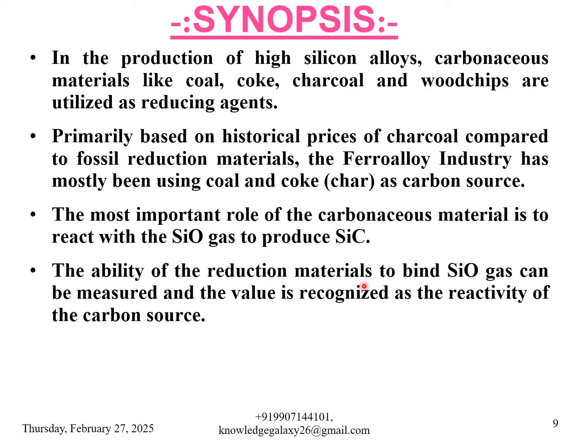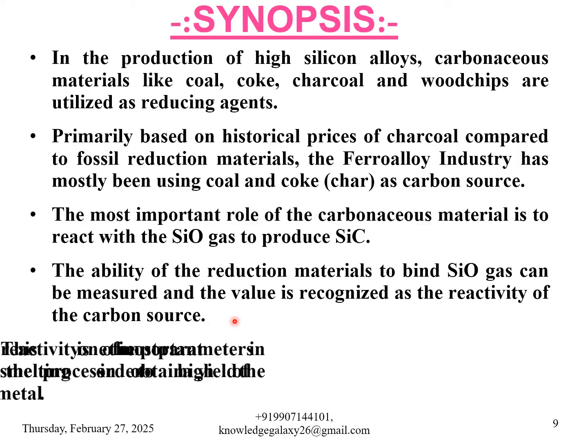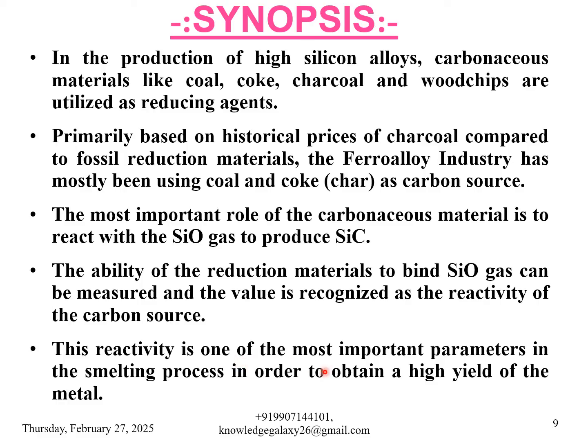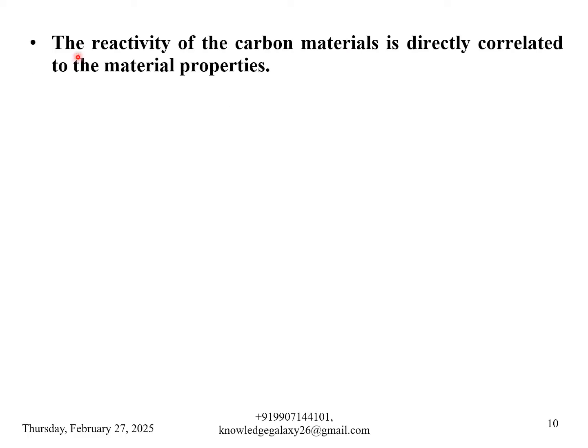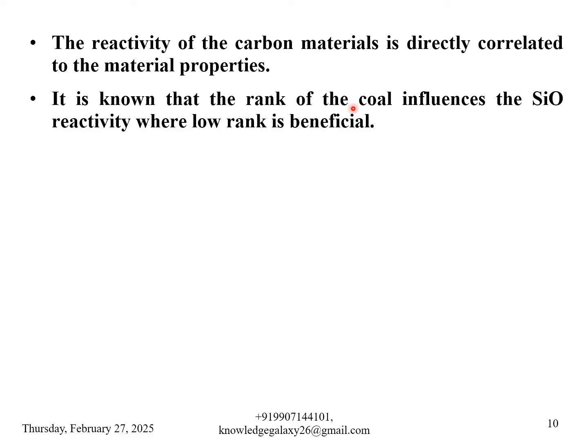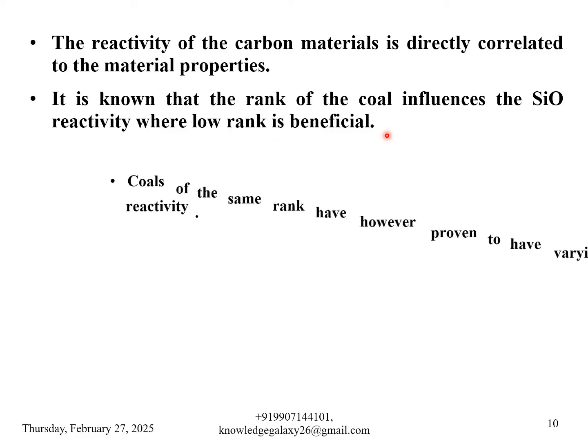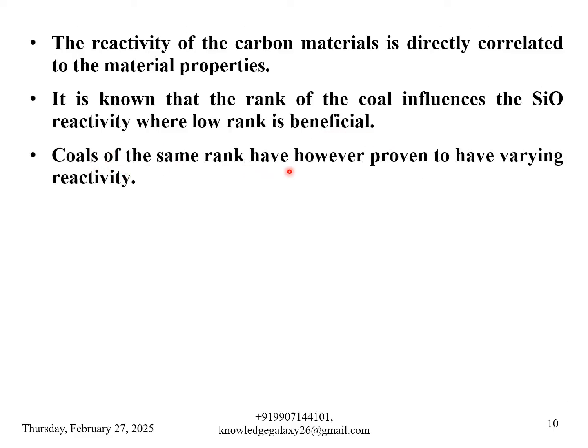The ability of the reduction materials to bind SiO gas can be measured, and the value is recognized as the reactivity of the carbon source. This reactivity is one of the most important parameters in the smelting process in order to obtain a high yield of the metal. The reactivity of the carbon materials is directly correlated to the material properties. It is known that the rank of the coal influences the SiO reactivity, where low rank is beneficial. Coals of the same rank have, however, proven to have varying reactivity.